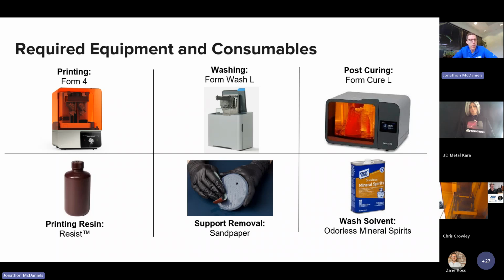The Resist, we're working on a scale up for manufacturing with Formlabs. There aren't any special requirements for post-processing. It's mainly support removal if you need to sand it or clean something up. That's simple enough to do. And for the wash solvent, we found that odorless mineral spirits is a good wash for this. It's got lower flammability than, say, your IPA. It works really well for this material.